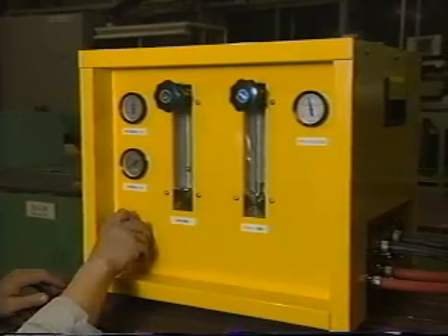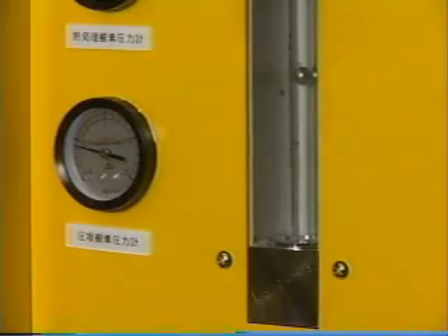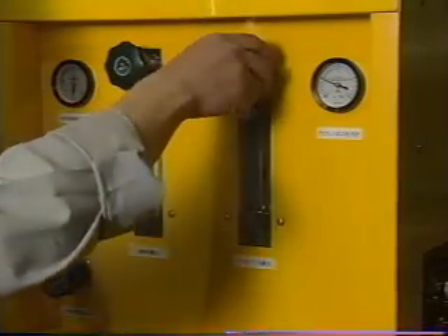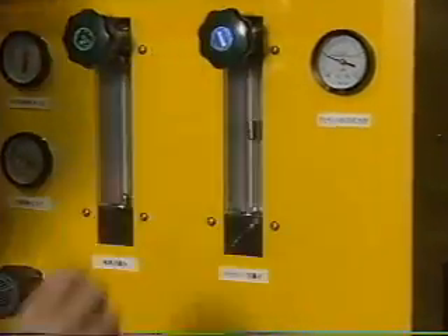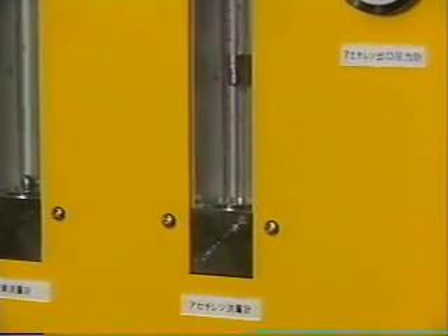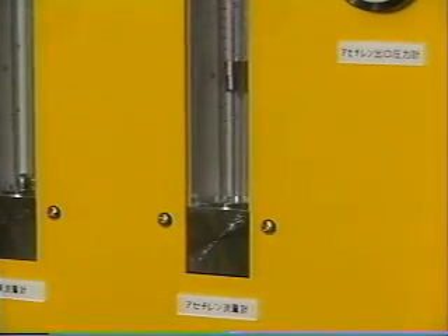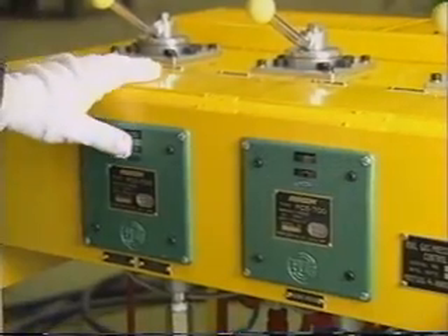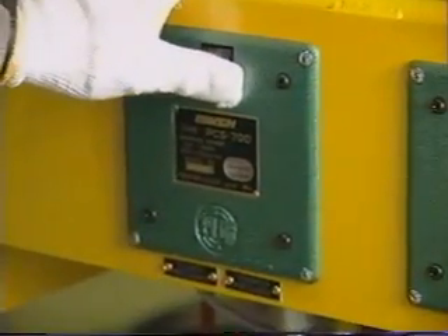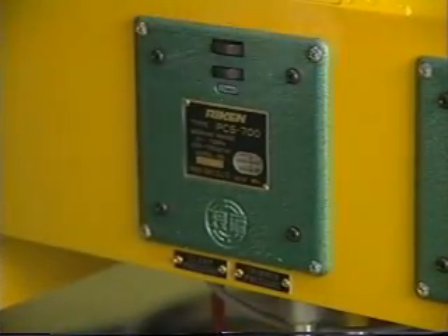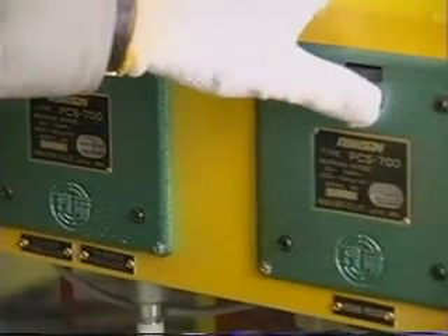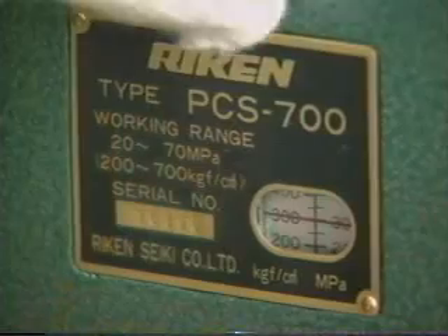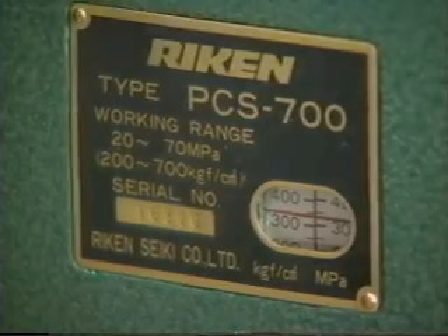This is how to adjust gas pressure. We first set the flow rate of oxygen gas by adjusting the pressure. The pressure of the acetylene gas is set to adjust the flow rate. After the adjustment of the gases, we're going to set the hydraulic pressure. First, we set the clamping force and the trimming force. Second, we set the pressure welding force.